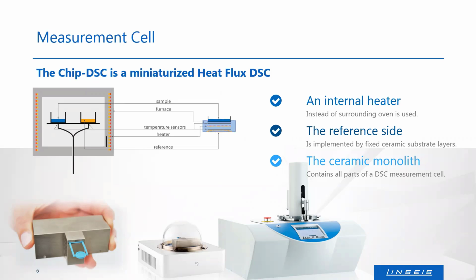At the top is still our crucible with the sample inside, and below you will find the temperature sensor for the sample. In the middle of our sensor, you will find the heater, so there's no surrounding oven anymore. Below that, you will find the temperature sensor for the reference, and at the bottom, the fixed reference. Everything is inside of one ceramic monolith, and this monolith contains all parts you need for a DSC measurement.